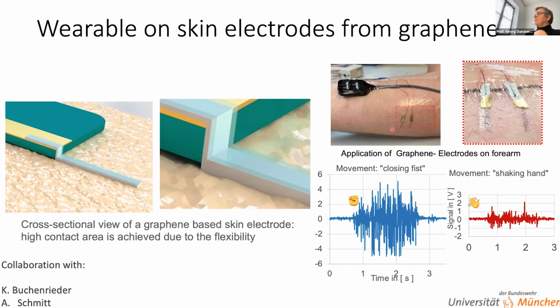We did it on the head, but here it's an image on the forearm, and here you see the graphene bits with a bit of tape on top. But at the end of the day, the graphene more or less adheres directly to the skin without any adhesive. And without going into further detail, we started to record first materials.